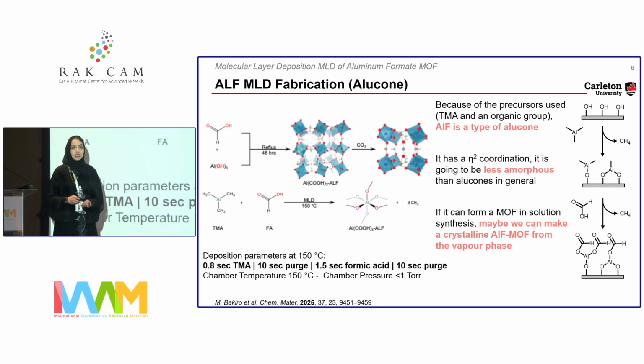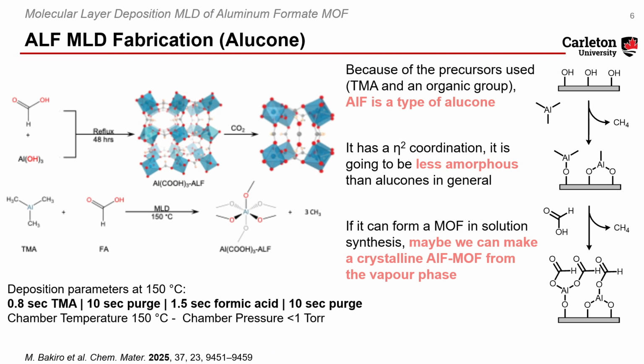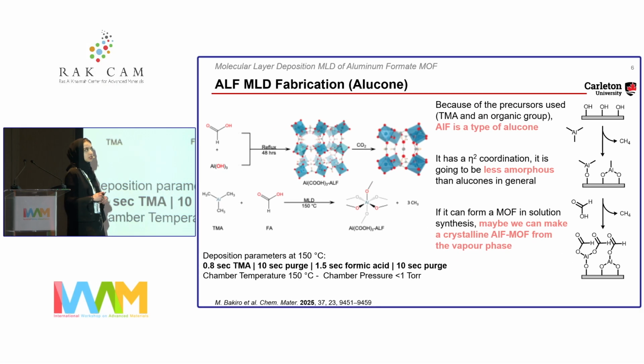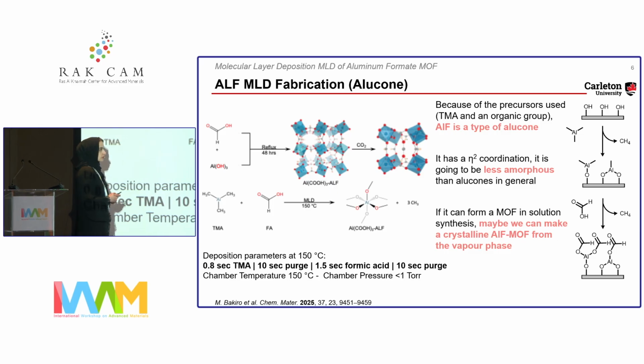Now this kind of material is already known. It's called metalcones. It's a hybrid inorganic-organic material synthesized by MLD. Oops, what's going on? Okay, sorry for that. It's synthesized by MLD, and it's known to be non-porous and non-crystalline. So what we wanted to do is to deposit this MOF. It's going to be alucone as deposited, non-porous, and see if we can crystallize it on the surface.